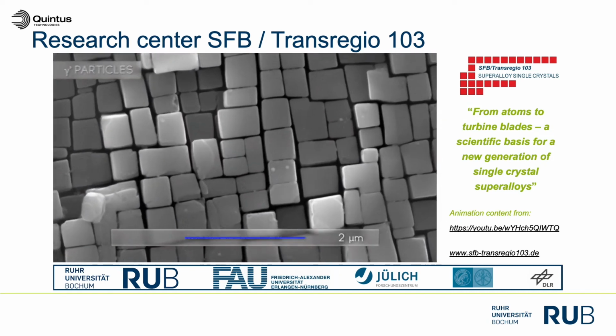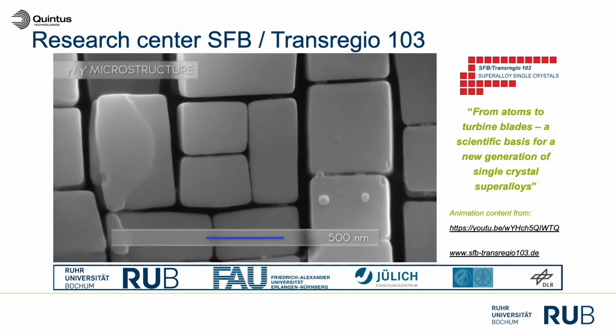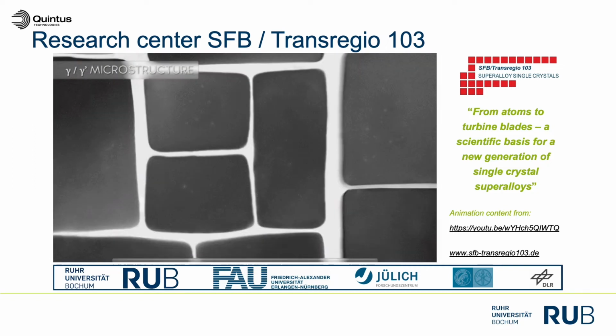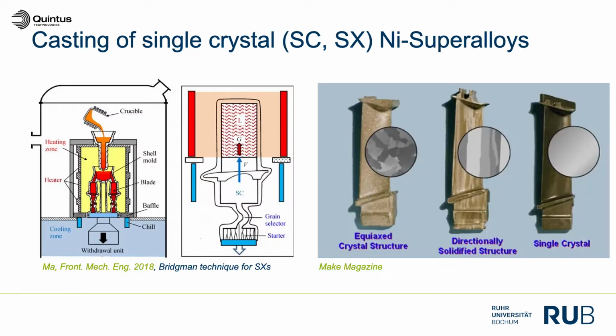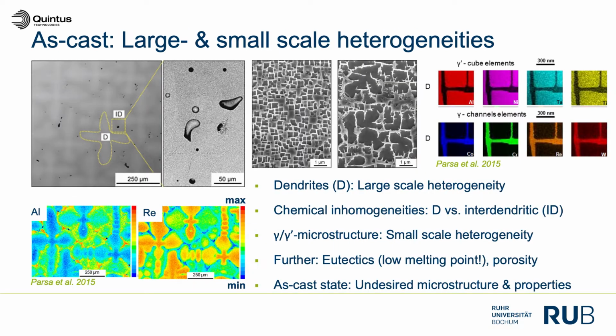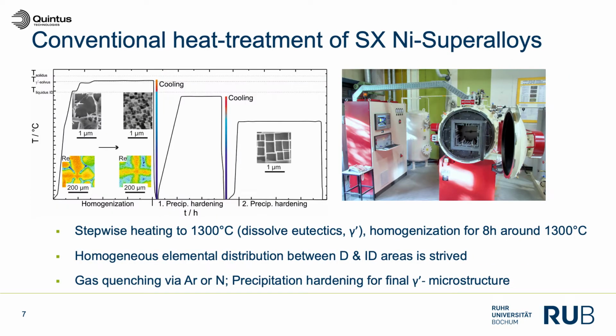In order to improve the properties of this class of materials, we can look at the processing routes. On a large industrial scale, they are cast as single crystals by using the Bridgman technique. During casting, porosity forms, we have a chemical inhomogeneity, and afterwards the material has to be heat treated in order to homogenize the materials. The heat treatment is done in a conventional vacuum furnace. And the problem here is that the porosity is still maintained. During homogenization, a new class of pores can also form, the so-called homogenization pores.